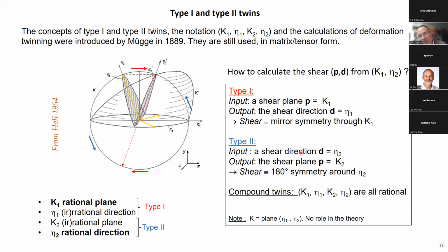It means that in my model, the shear direction is the input. Okay, it's eta 2, it's the shear direction. And the output is the shearing plane, K2. And I can notice that in that case, the parent and the twin phases are related by a half turn